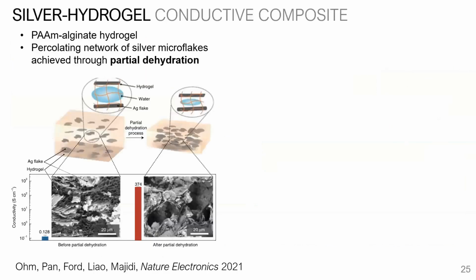So how do we make these materials conductive? Well, of course, a lot of you who have worked with these gels know that you can make ionic gels, depending on the type of solvent that you use, which is great for a lot of bioelectronic applications. But ionic gels don't have the conductivities needed for any kind of digital circuitry. And so what we wanted was to make conductive gels that actually have electrical conductivity that could be used to support any surface mount and microelectronic components.